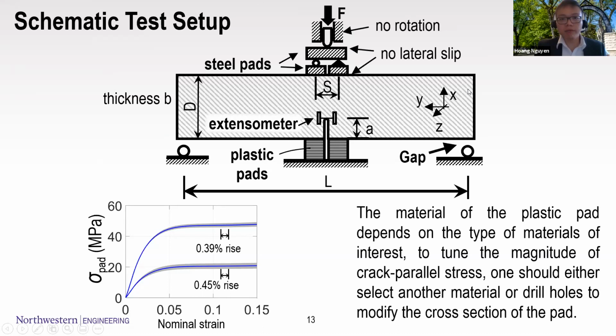A more detailed schematic of the setup is shown here, with some steel pads, and there are technical requirements here: you don't allow rotation and slip in the experimental configuration. And for the plastic pad, because of no rotation here, we can conserve the symmetry, which means equal deformation on the plastic pads. And as I mentioned previously, there's one requirement for the plastic pad. It is supposed to give a constant pressure, or constant crack pillar stress, here.